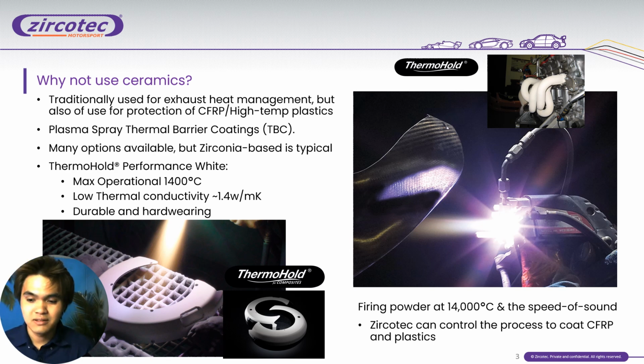It can, if you are not able to control the flame. By making quick passes, at fast speeds, you can essentially cool the plastic down quickly enough so that the heat will only go up to a max of 100 degrees and allow the ceramic to stick to the material. As long as the material can withstand 100 degrees, we can plasma spray pretty much any material, any metal material, but it will depend on the surface.